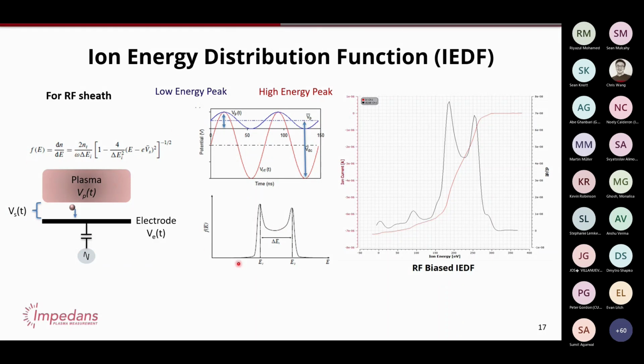But if your RF is oscillating more slowly, the ions have more time to react to the differences, and the peak splitting is worse or larger. Worse or better, depending on your perspective, but it's larger. Or if the frequency is very, very high, the ions can't react. So on average, they just see some DC potential, and you have almost no visible peak splitting.